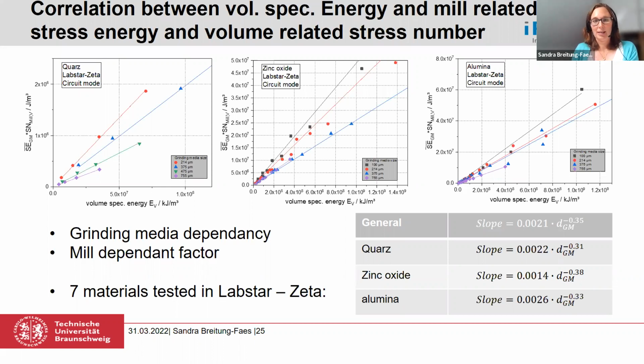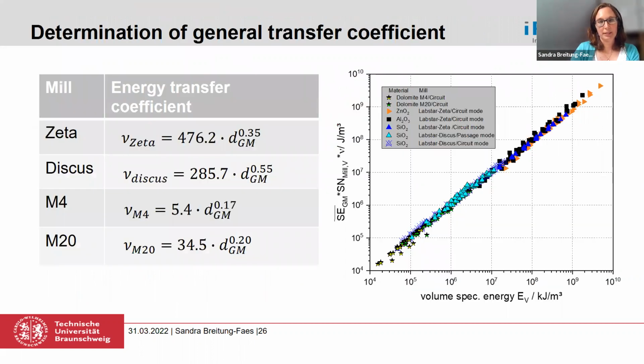And then I decided, okay, I make a mean value out of it and take a general correlation for the slope of these curves, which is shown here. And when you do this, and I did it also for the other mills, this is the result. You can see that you have a pretty good correlation if you introduce this nu factor here, which can be described by these power functions. When you look at the power functions, to be honest, I didn't see any correlation where I could say, okay, the size seems to influence it in this way or in that way. I can't say there is some rule I can give you here at the moment. Maybe you have an idea how to do it, but for me it was not clear. But at least it works.